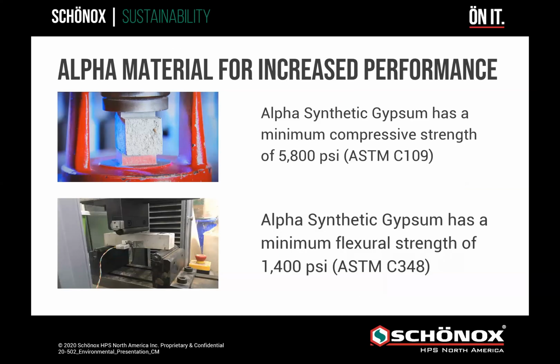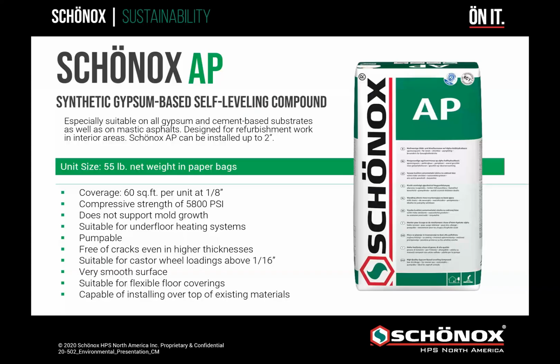So alpha synthetic gypsum has a minimum compressive strength of 5,800 PSI after 28 days when tested with ASTM C109. Alpha particles will also give you a minimum flexural strength of 1,400 PSI using ASTM standard C348. Normal concrete installations in today's environment normally have a compressive strength close to 3,000 to 3,500 PSI, and flexural strength close to 1,000 PSI. So with the alpha particle system, with our synthetic, we are not only reducing emissions from power plants, but now producing a material almost twice the strength of normal concrete, with higher flexural strength as well.